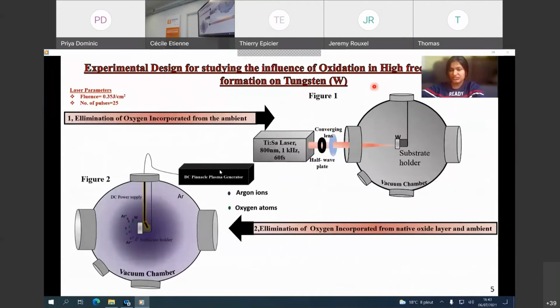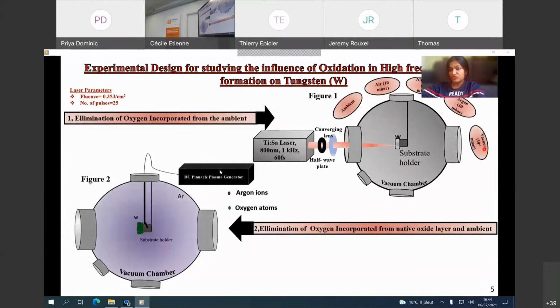And in figure 1, you can see the basic experimental setup, which consists of a vacuum chamber, and we have a well-polished tungsten surface, and we are focusing a titanium sapphire laser of 800 nanometer wavelength, 1 kilohertz repetition rate, and 60 femtosecond pulse duration for the production of high spatial frequency LIPSS or HSFLs. And in order to study the influence of oxygen or different gaseous environments on the formation of ripples or HSFLs, we are doing this experiment for 5 different gaseous conditions. So the first one is ambient normal atmospheric surroundings, and then air at 10 millibar, then nitrogen at 10 millibar, argon at 10 millibar, and vacuum at 10 raised to minus 7 millibar.